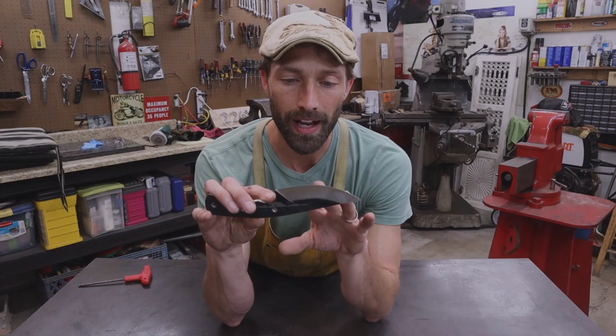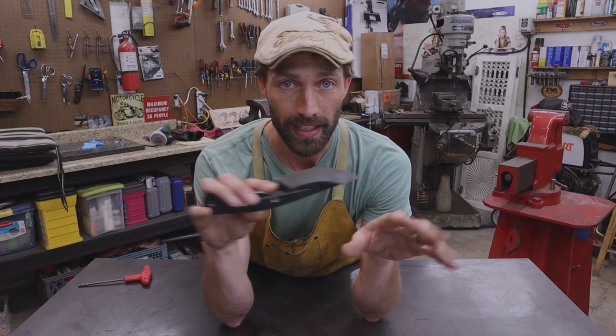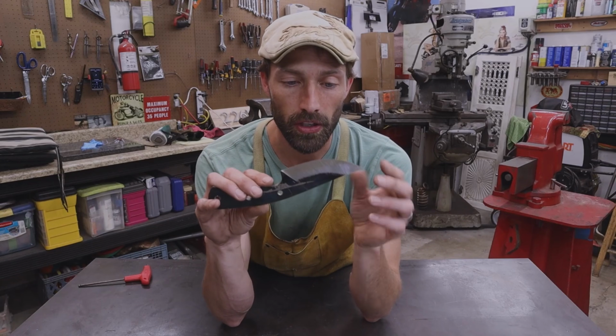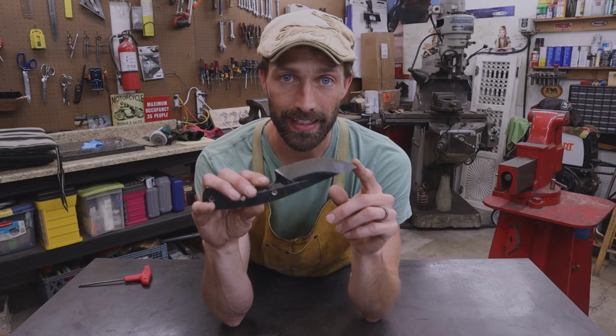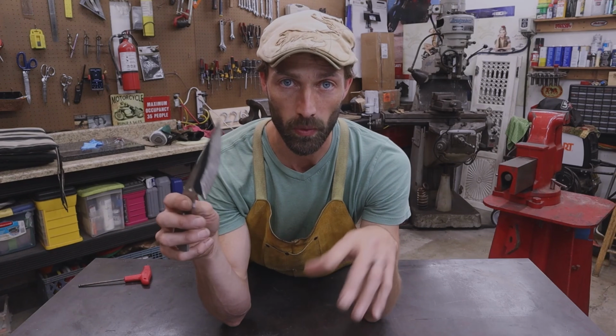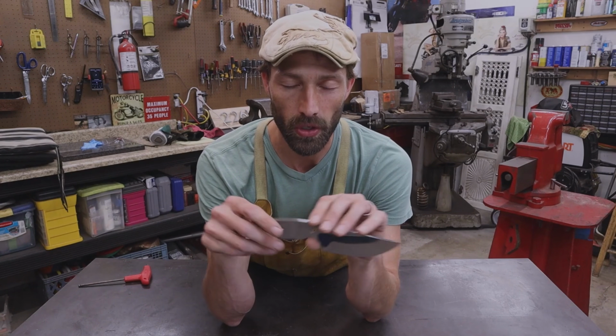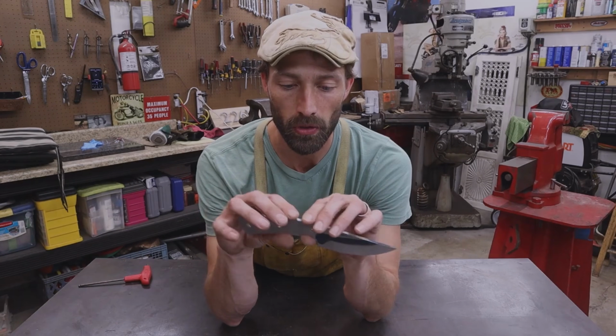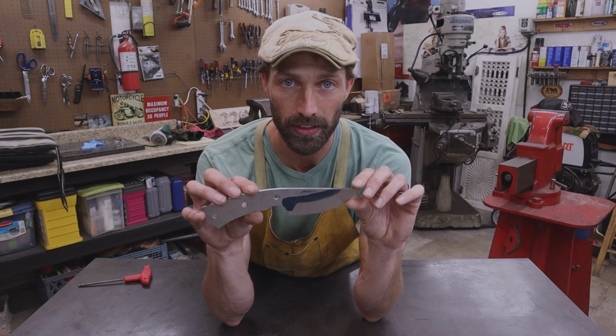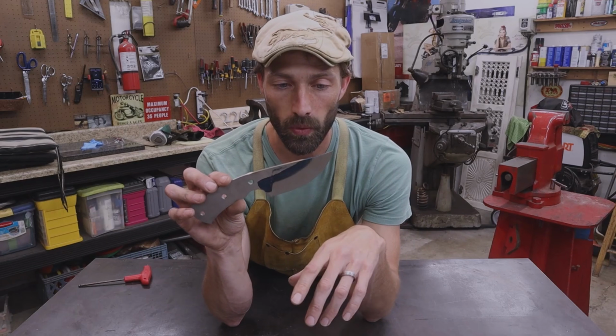So I run my knife in the forge at a low heat until the entire blade goes non-magnetic, and I heat it just slightly longer, and then I go in for a quench in a preheated quenchant oil. Tonight we're gonna use canola oil heated up to about 125 to 130 degrees. And we're gonna quench this knife.